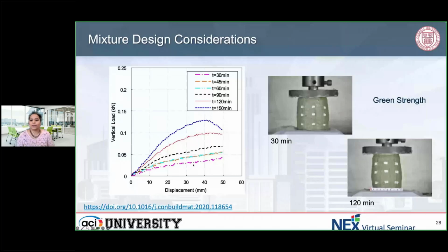This also gives you an indication, when you print your material system, of how much load it will be able to carry, which is basically the other layers being placed on top of it, or the robotic arm pushing the material down on top of the other material. So there are forces acting on the bottom layer that has been deposited. So green strength is really important and gives you a lot of information about how your printed structure is going to behave.